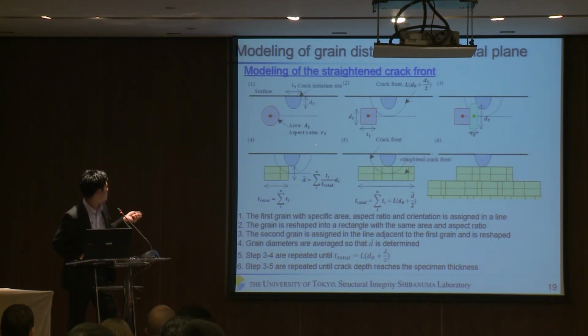And so, in the next step, these steps are repeated until this equation is met. So this length is the same as this semi-elliptical crack front. And these steps are repeated until the crack depth reaches the specimen thickness.